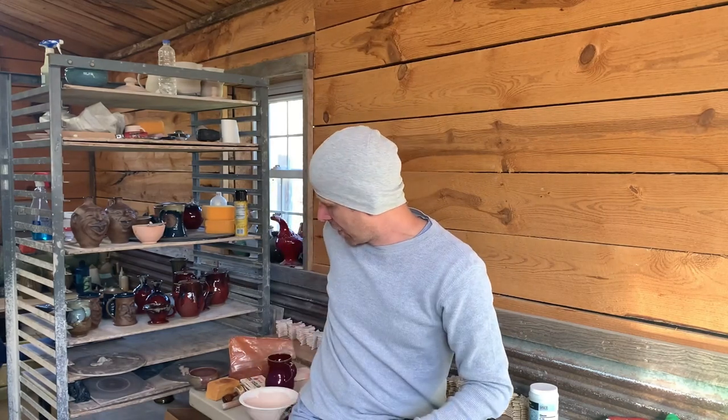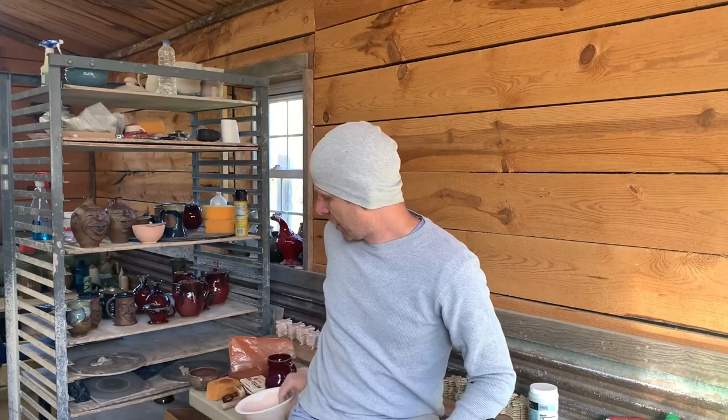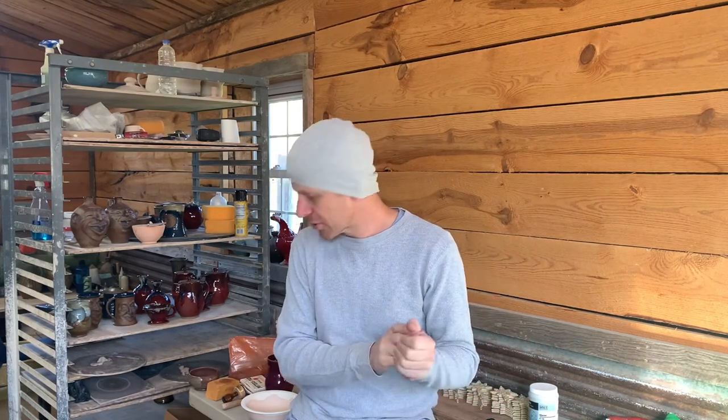As you can see on this bowl, that bottom glaze is put on uneven, and if I were to glaze red completely over it, it would run much like that. The red is very finicky — it can sometimes be red, sometimes green, sometimes somewhere in between. That has largely to do with the thickness of the glaze and where it sits in the kiln, because that red requires a reduction atmosphere in my gas reduction kiln to achieve that specific color.